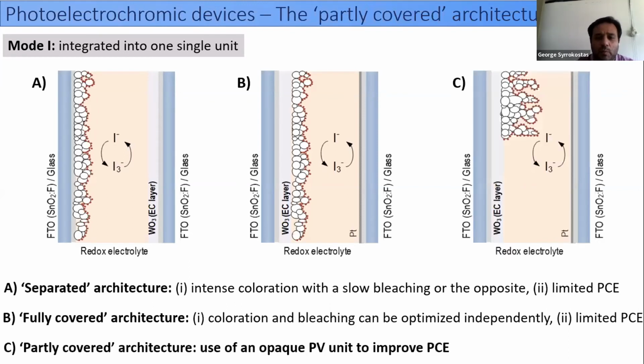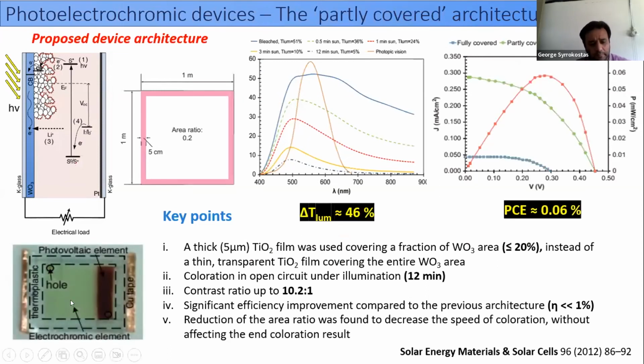So we proposed to use a very thick, non-transparent titanium dioxide film placed at one side of the device in order to improve the photoconversion efficiency. And here on the left bottom side of my presentation, you can see such a device with a non-transparent photovoltaic element that is now placed out of the optical path at one side of the device. We achieved an optical modulation around 50% in a few minutes,